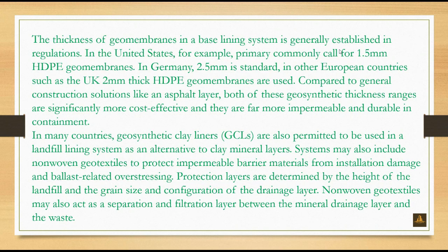In Germany, 2.5 mm is standard. In other European countries such as the UK, 2 mm thick HDPE geomembranes are used. Compared to general construction solutions like an asphalt layer, both geosynthetic thickness ranges are significantly more cost-effective and far more impermeable and durable. In many countries, geosynthetic clay liners are also permitted to be used in a landfill lining system as an alternative to clay mineral layers.